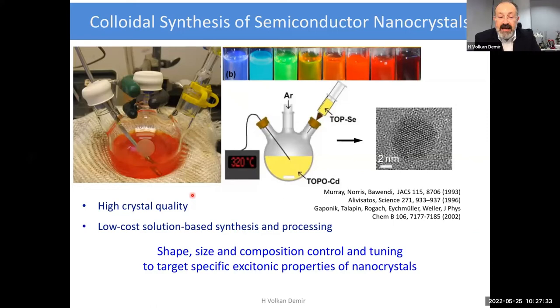Coming from conventional epitaxy background, for me, it is always so impressive with such low cost setup, how high quality material we can achieve. And this is, in my opinion, one of the greatest strengths of such semiconductor nanocrystals, because they are solution-based synthesized, which means they are also processed in solution. And this opens up a completely new venue for us to apply them in large area if we get the processing conditions right, at very low cost. So these are quite applicable for large area applications, provided that the conditions are achieved.